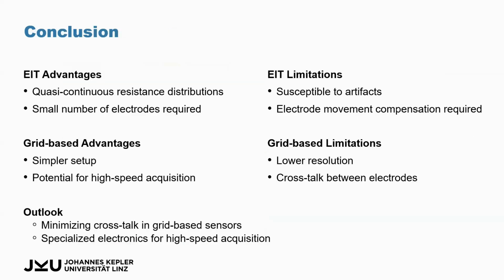So for the conclusion, we have some advantages of the EIT, which is that we have a quasi-continuous resistance distribution, and we just need a small number of electrodes. The challenges that we're having are, first, it's very susceptible to artifacts, so it matters a lot how we are doing the reconstruction, which parameters we are using. And what we haven't considered in the study presented here is the electrode movement. So in literature, there have been many sensors, for example, force measurement, like touch sensing, which use EIT, but there the electrodes don't move. In our system, if we go to 50%, 100% strain, the electrode movement is quite significant. And we have to take that into account to not confuse resistivity change and just geometry change.